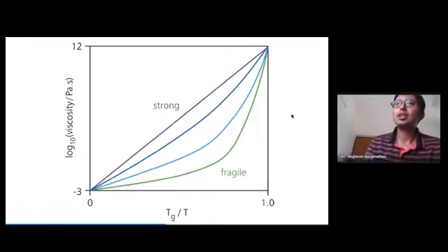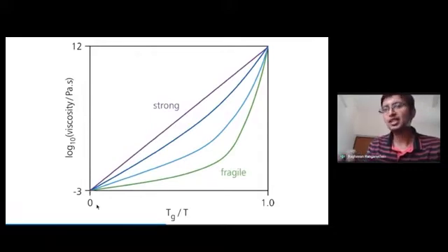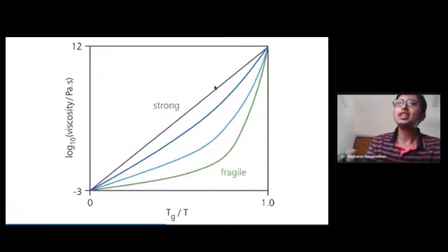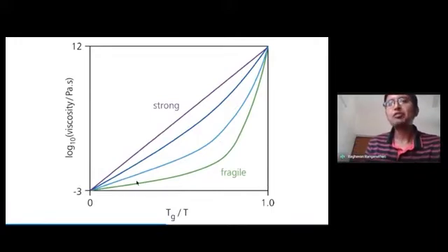So in other words, when you're cooling this material, that is, you're moving from left to right, the temperature is decreasing from left to right. You see that the viscosity essentially shows either very strong scaling, what are called strong glasses, or a very weak scaling, that's called a fragile glass. And we won't go into the physics of why such glasses show this behavior, but it suffices to know that viscosity is a very, very sensitive parameter that depends on the temperature.